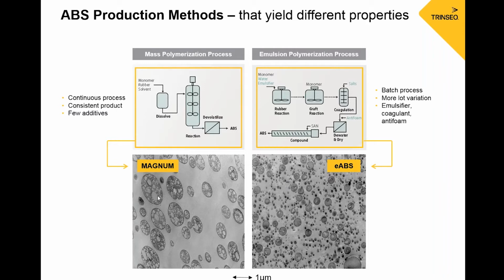So what we see here with the mass ABS, the rubber particles have these large occlusions in light gray, so it has the SAN matrix inside the rubber particle itself, and that allows for a higher efficiency of the rubber with respect to the toughness or impact resistance. So the toughness comes from the total phase volume of the rubber, and the SAN occlusion in the rubber is included in that total phase volume.